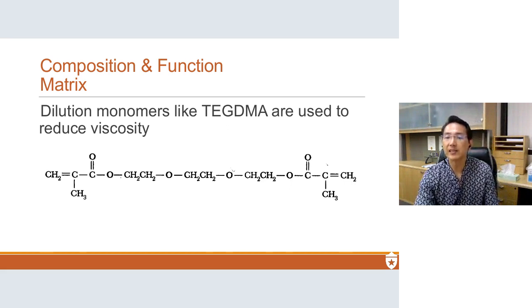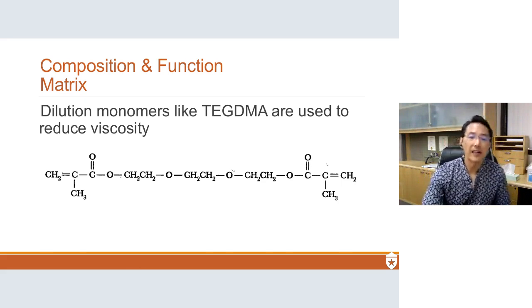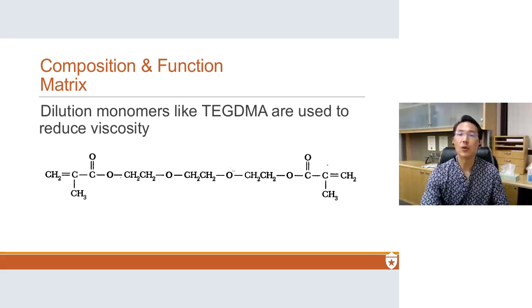generally a very typical formulation of BIS-GMA and TEGDMA is either a 70-30 BIS-GMA to TEGDMA ratio or about 60-40. And this is a 70-30 BIS-GMA TEGDMA. So now it flows, right? While before the BIS-GMA was really, really thick. It's not solid, but like honey, not even the ones that you squeeze out from the little bear. I mean, we're talking like those that come in the jars where you have to scoop it out. It's very, very sticky and very, very thick. Okay, so that's what they do. They use TEGDMA to make it more flowable and mixable with the filler. So that's the matrix monomers.